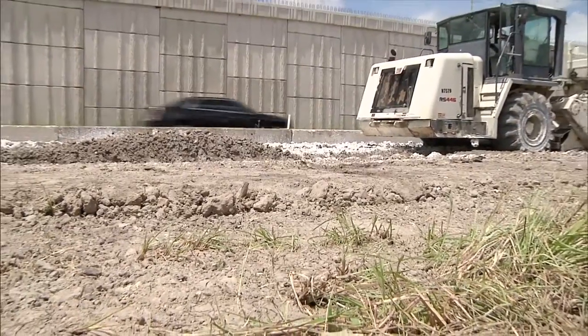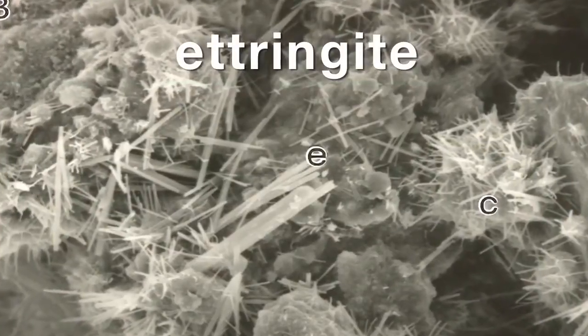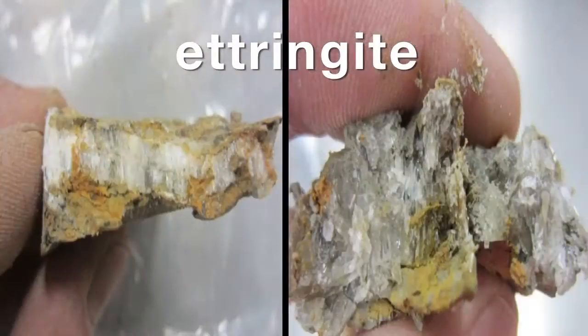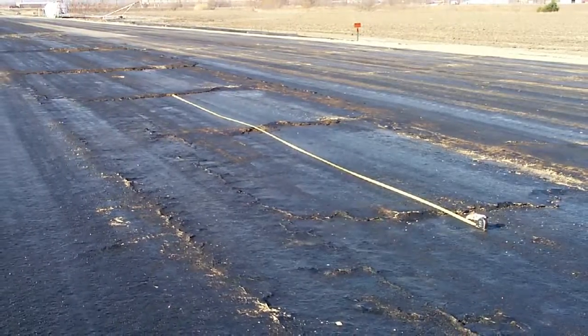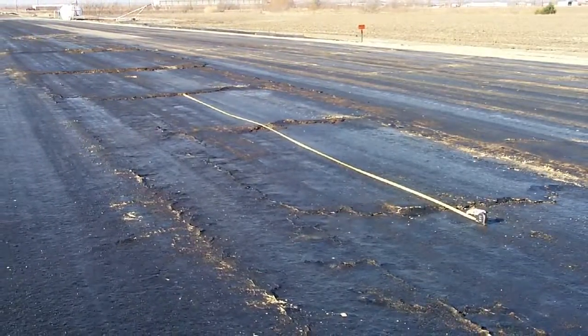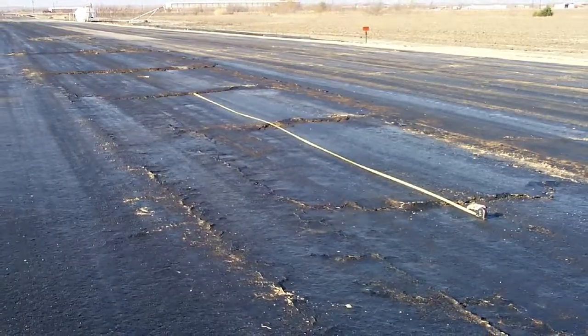So if you have the sulfate in the soil, when you add in lime, lime is going to react with the gypsum. Some of the reactions between lime or cement with the soil sulfates and also soils itself cause a compound called ettringite. This ettringite, whenever it gets hydrated, it actually doubles up its volume. So whenever that happens in a soil, the pavement starts heaving up and you will see a lot of bump-related cracking happening on the pavements. So the pavement has to be constantly repaired.